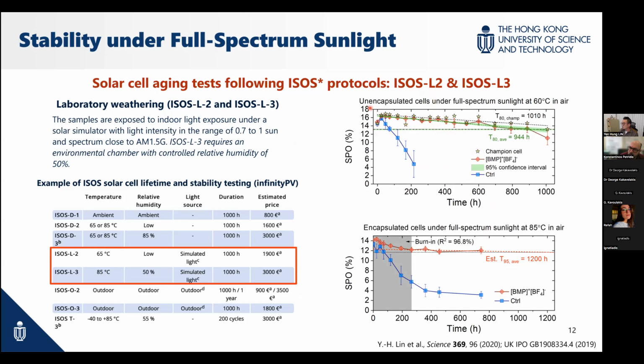The upper one is unencapsulated cells, and we do it under full spectrum sunlight, basically matching the solar spectrum, at 60 degrees Celsius in air. And as compared to the reference, the data shown here is the one where we encapsulate the cell, but using exactly the same aging machines under the full spectrum sunlight at 85 degrees in air.